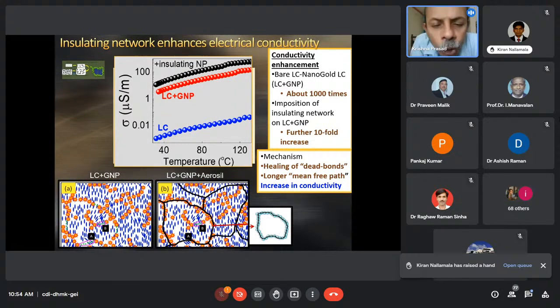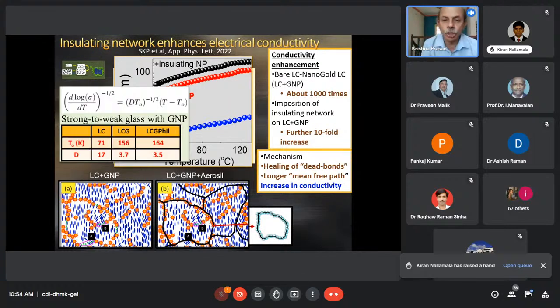So the contact between the gold nanoparticles is not constant with time, but when you impose the thixotropic network, that action is frozen to a large extent, at least wherever the thixotropic network exists. Therefore you are not allowing the system to have thermal fluctuations wherever the gold nanoparticles are present, and we call this patching up or the healing of dead bonds. And therefore the mean free path, if you talk in terms of solid state physics, in the system increases, and so you end up with a better conductivity in the system.